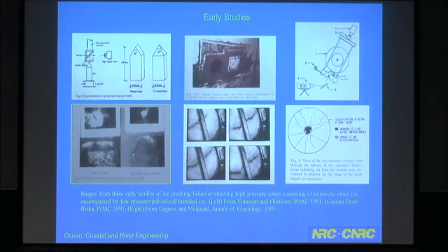What we saw was very similar to this, only not linear, because the shape of the ice was different. We saw the hard zone regions surrounded by crushed ice, and these are just the peripheral cracks on the sides. But actually, this paper was the first discussion of the slurry layer in the literature that I'm aware of. I don't think anybody else had anything to say about it prior to this paper. I'll say quite a bit more about that as we go along.